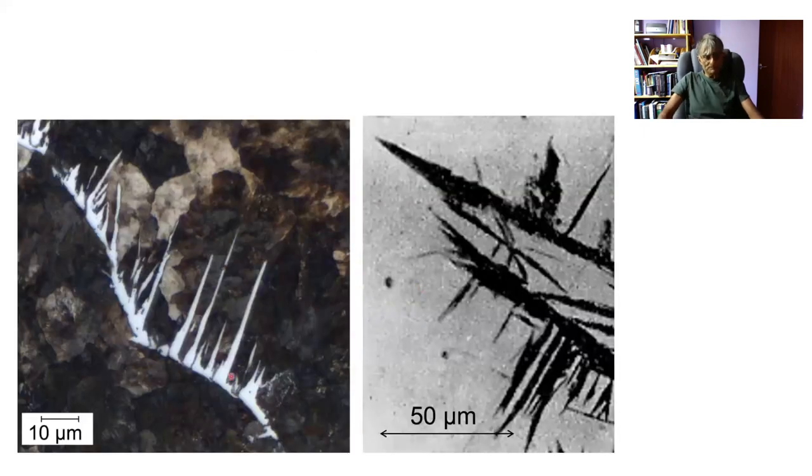Now, I pointed out to you, if you look at an optical micrograph of Widmanstätten ferrite, you see clean plates which etch white, okay? This is in contrast to the images I showed you for bainite on a similar sort of scale, where they etch extremely dark relative to the background, which in this case is untempered martensite. And that's because, as we saw in lecture 3, what appears to be a single plate of bainite has thousands of little platelets in it. And all the resulting interfaces are therefore attacked by the etchant, and therefore in optical microscopy, the bainite appears dark. It's a reflection of the intricate structure present inside what appears on an optical scale to be a single plate of bainite. So the clue is that this cannot contain much structure, all right? Inside a plate of Widmanstätten ferrite, there cannot be much structure.